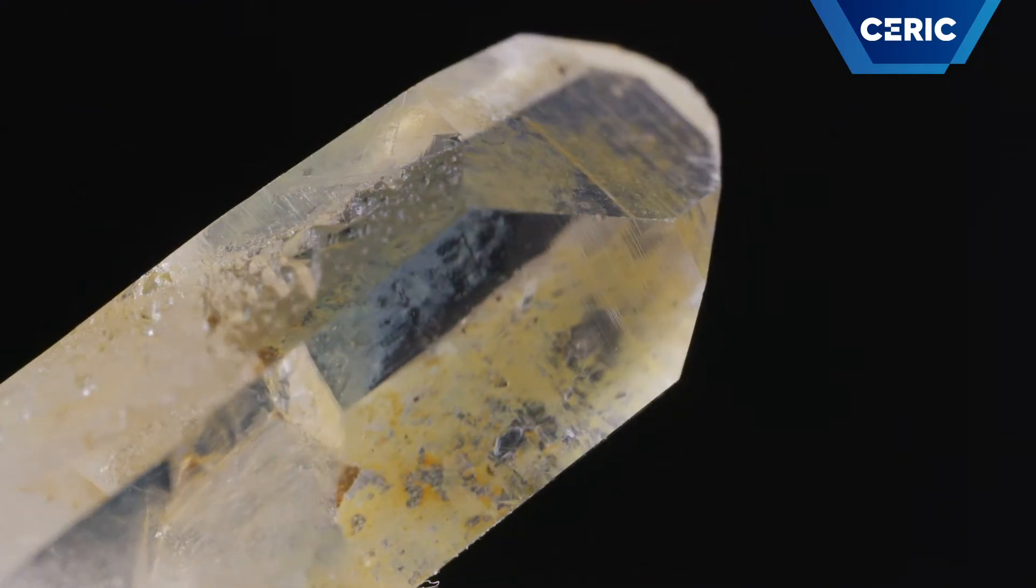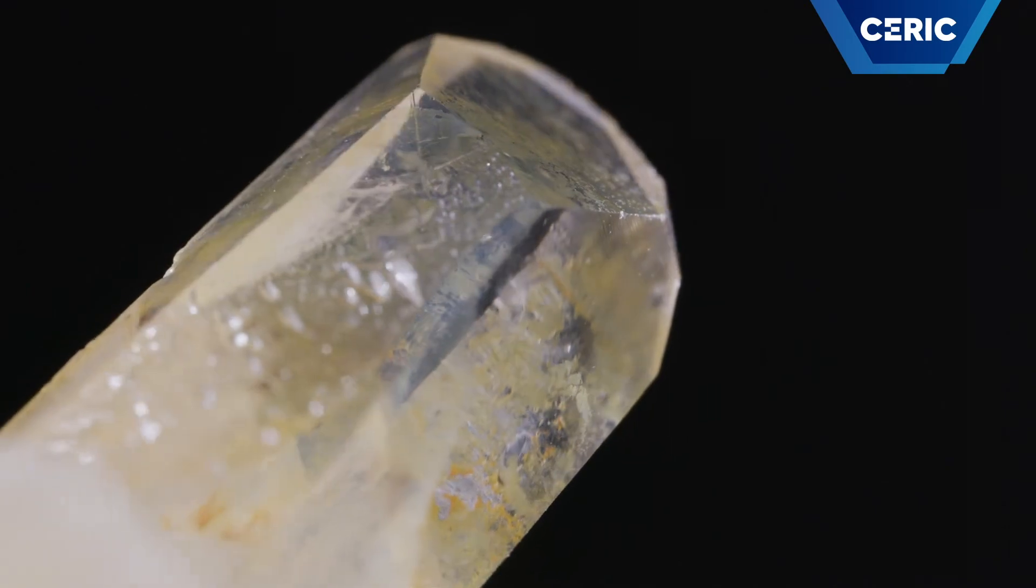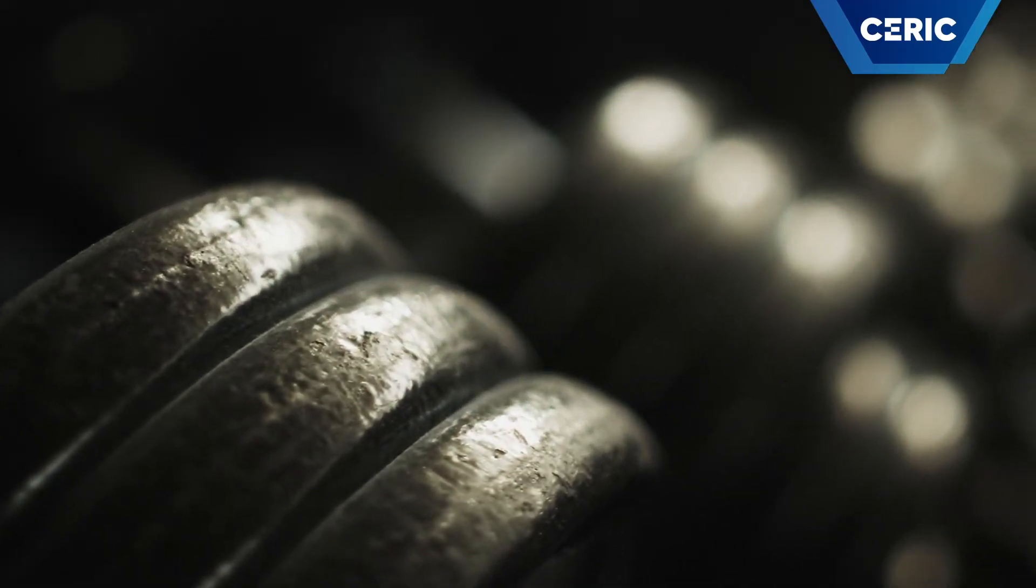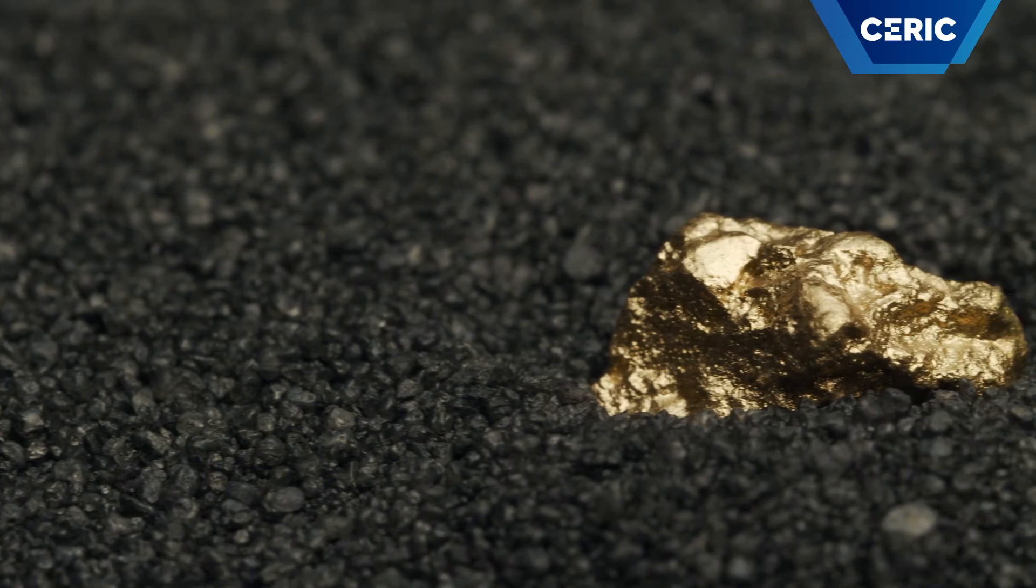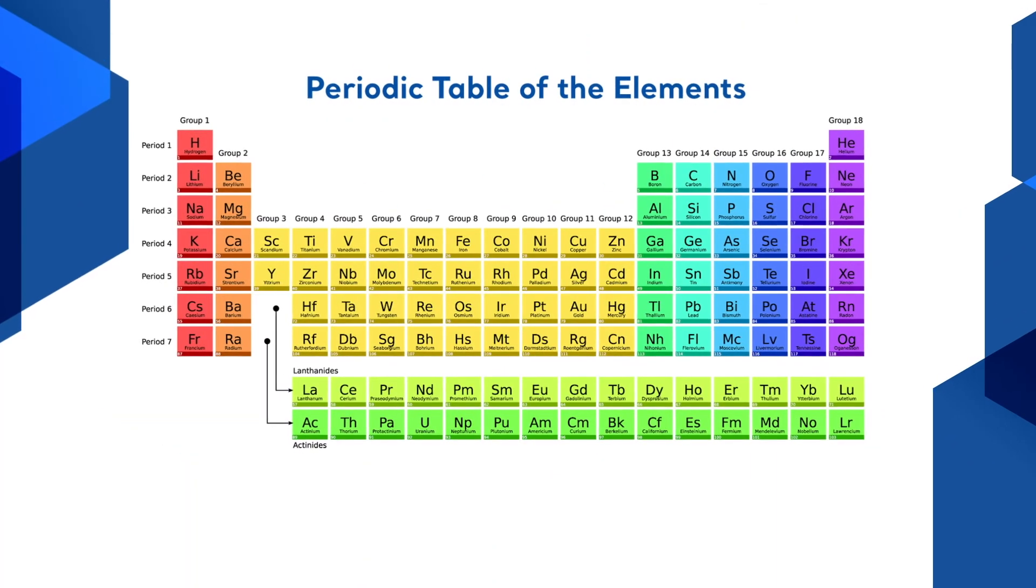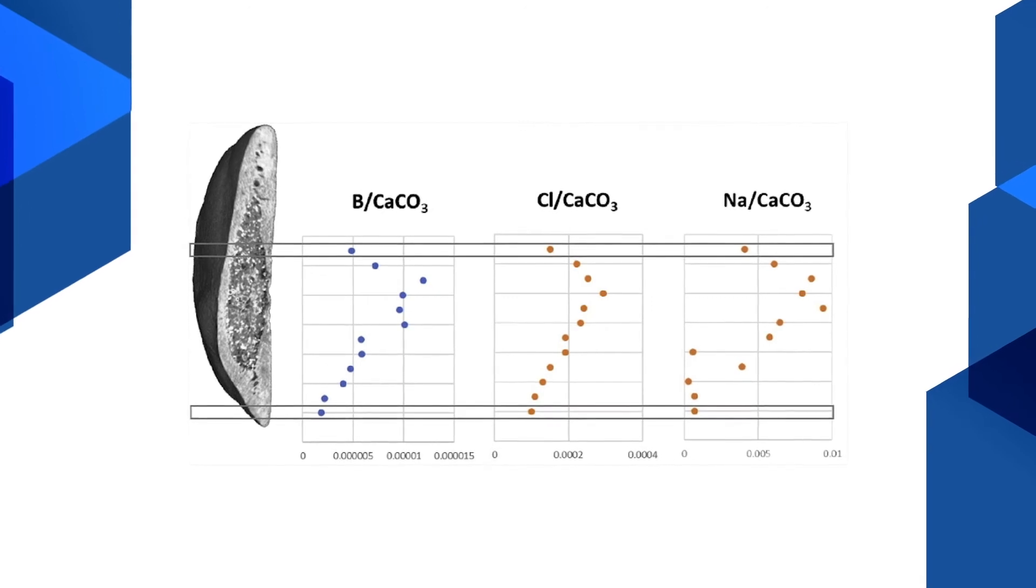Typical materials we analyze for composition are silicate, ceramics, glasses, metals like iron, bronze, or noble metals. Most of the major and minor components, as well as a few trace elements, can be quantified. Unlike competing techniques, it is sensitive to light elements such as hydrogen, boron, or chlorine.